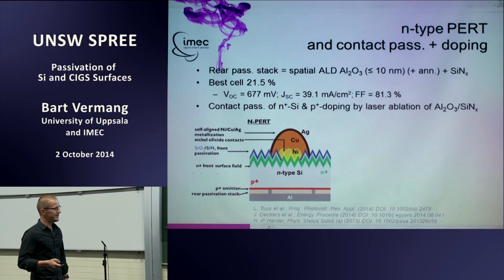The other thing is, so we have been passivating in between contacts for a long time, but now, especially with ALD, you can deposit very thin layers. So you can make a kind of tunneling layer in between a metal contact and your silicon. So you can even start to passivate your interface at the metal contact. And that's something else that they have been working on and getting decent results.